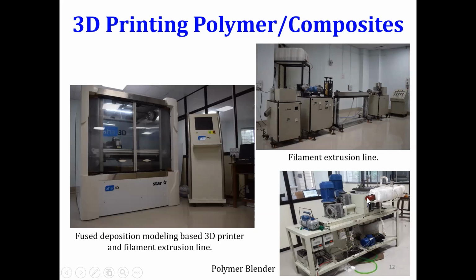Please do note that the outcome of the polymer blender or a twin screw extruder is never uniform. And what we need for a 3D printer, as I said, is 1.75 millimeter plus minus 50 microns or 2.85 plus minus 50 microns, or any diameter based on the requirements or nozzle diameter, plus minus 50 microns. Plus minus 50 microns is not possible to achieve on a twin screw extruder, because in twin screw extruders or these polymer blenders, pressure variation is large. And thereby, though the output comes in the form of a wire, the diametrical variations are really high. So we use these polymer blenders or twin screw extruders only to blend and have a wire of variable diameter, chop it and put it in a single screw extruder, wherein we can maintain plus minus 50 microns easily.